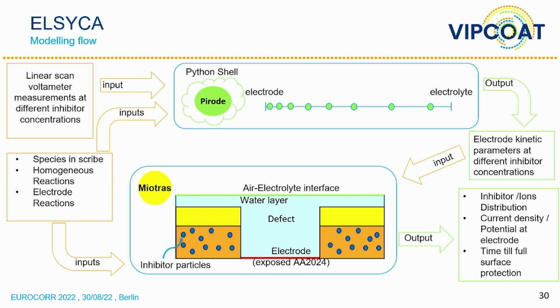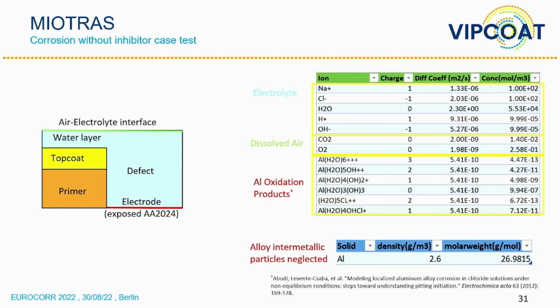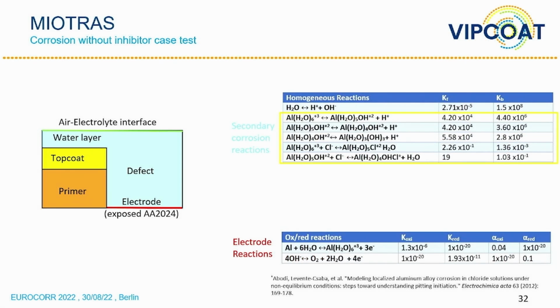So in fact, here you see a little bit how this is done. We take into account all the ion interactions. We have that at the moment for zinc, for iron, and for aluminium. So this allows us to calculate as a function of time the concentration gradients, because we solve for the mass transport. We take into account the electrochemical reactions, and then out of that we can calculate the system.